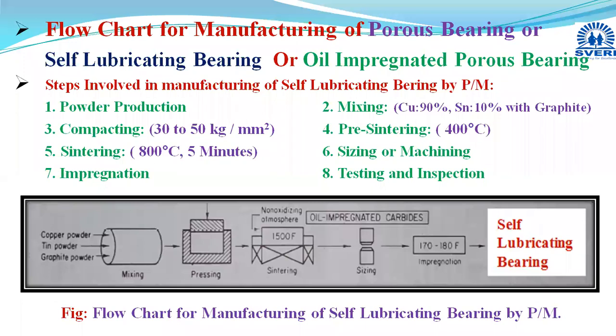Then that green compact is subjected to the sintering stage. In this, we heat the component at a higher temperature for a few minutes to a few hours, depending on the composition of the material and the desired shape and size. Sintering is completed in three stages: diffusion, densification, and recrystallization and grain growth. Then sizing or machining is done. During sintering, some change in shape and size may take place. To correct it, we do the sizing operation, or sometimes machining.